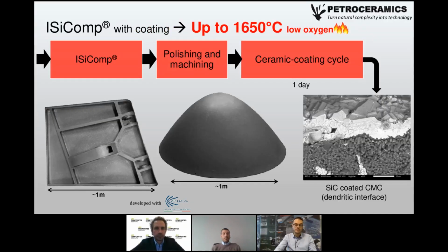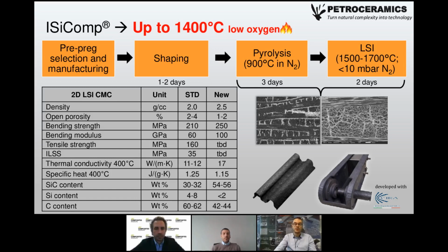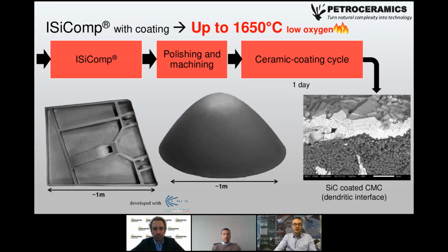ISiComp can withstand prolonged exposure up to 1400 Celsius degrees in inert or low oxygen atmospheres, and for this reason, it is the fitting composite for some aerospace applications. With ISiComp, we developed, together with the Italian Center for Aerospace Research, CIRA, some components of the Space Rider vehicle of the ESA. To better protect our ISiComp from extremely wearing conditions, we developed an innovative silicon carbide coating.